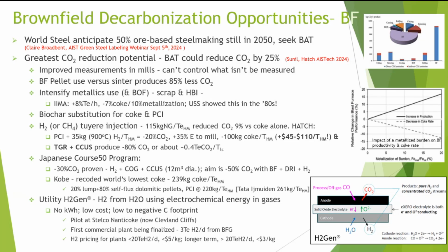We need to intensify metallics use in the blast furnace, either scrap or HBI. The IIMA, the International Iron Metallics Association, showed an 8% productivity increase and a 7% coke reduction for every 10% metallization that was put in the blast furnace. And US Steel actually showed this back in the 80s when they were putting metallics into the furnace. Biochar substitution, of course, for coke and pulverized coal injection. Hydrogen or methane tuyere injection.